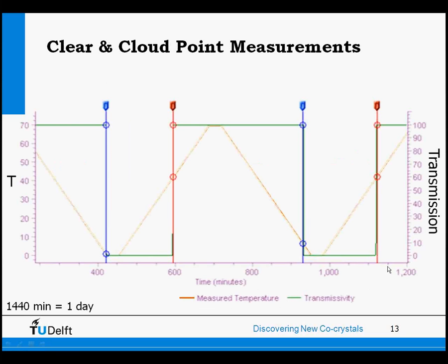And that is shown in this graph: the temperature against measurement time. The orange line is indicating the temperature profile we are using. So you cool down, and at some point you get a suspension, and then you heat up, and at some point you get a clear solution, and then you get 100% transmission. That's on the right axis, the green line. At the point where you have 100% transmission at the temperature, that is your clear point. The clear points are indicated by the red marks. And you can determine the saturation temperature from that.